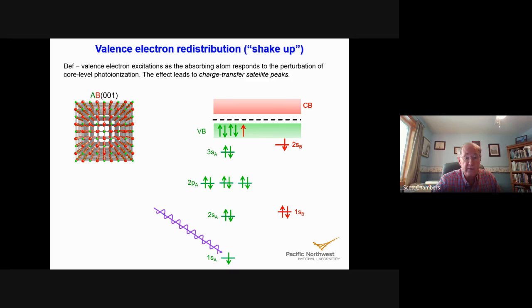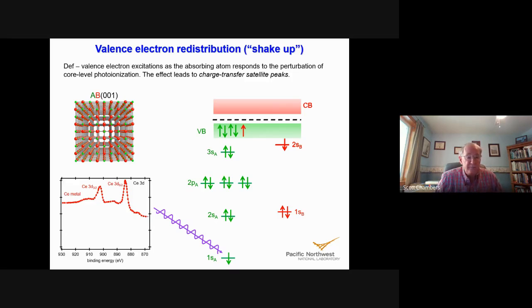As an example, let's compare cerium metal. There's cerium metal, and this is the 3d peak. There's the spin-orbit split, 3d5/2 and 3d3/2, and then there are some weak features on the higher binding energy side. Those are probably energy loss features in the metal.